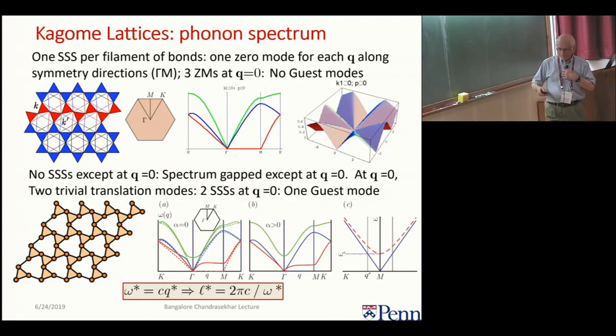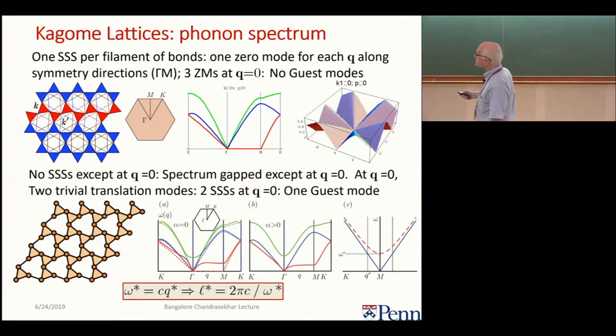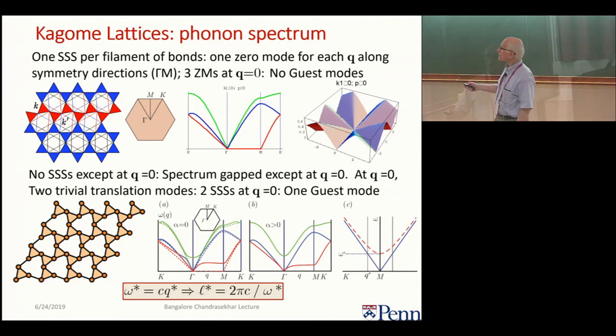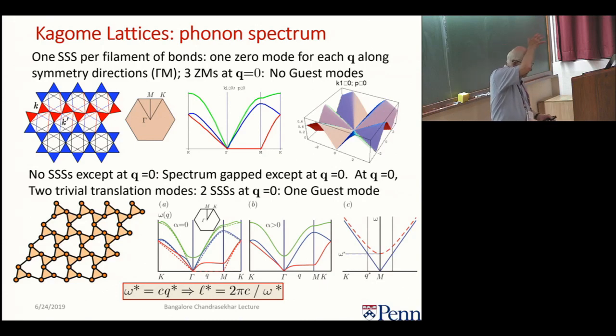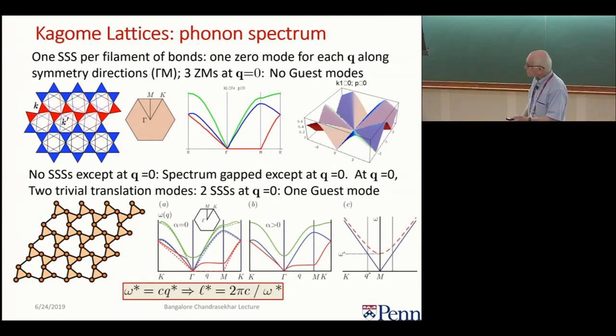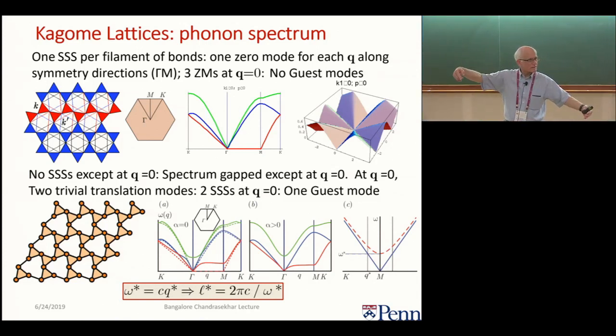So let's look at the Kagome lattice. The red here represents the zero mode, which I'll talk about in a moment, but ignore that and just assume it's the same as the blues. So this is characterized by grids of straight lines that go along the three directions of a hexagonal lattice. Remember, these things are under periodic boundary conditions, so you can think of them as being wrapped on a cylinder or on a torus, ignoring any Gaussian curvature that comes out of that model. And so each of the straight lines of bonds carries with it a state of self-stress. And the number of those straight lines is 3 square root of n, where n is the total number, because it's just lines, it's not points everywhere. So that tells me that I have to have that many zero modes in the spectrum.